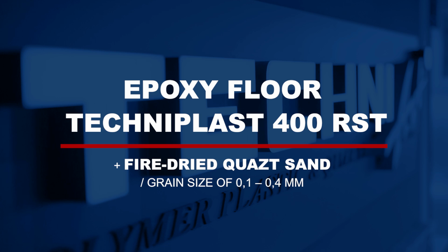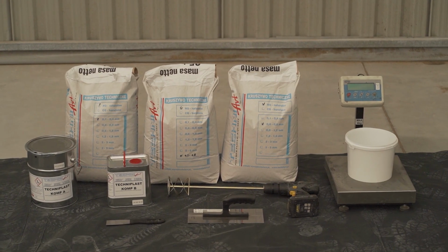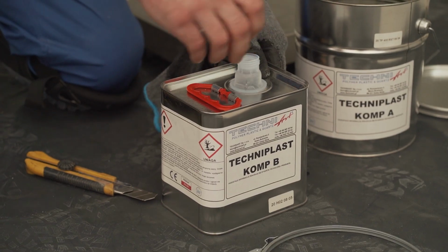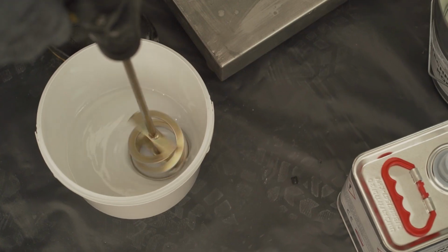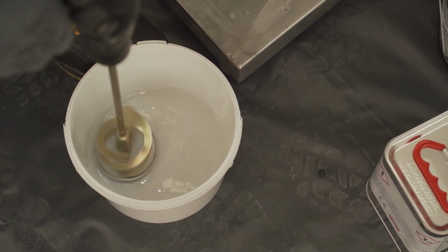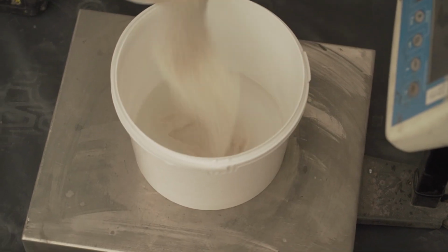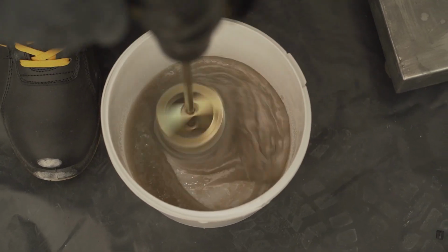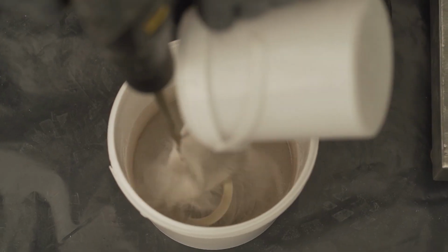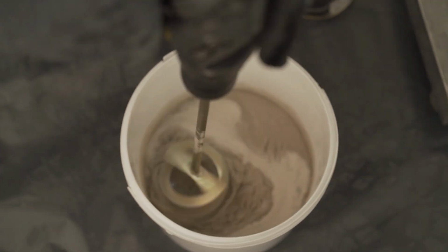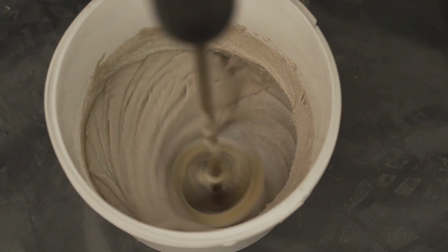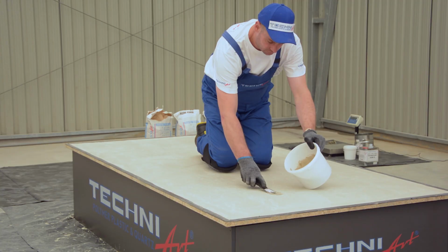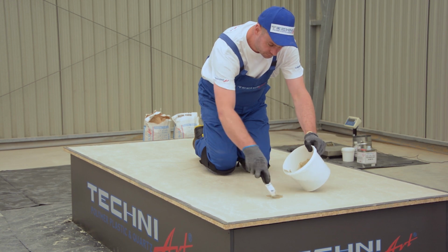The next step is to prepare the compound for filling losses and cut cracks. To prepare the putty, use the TechniArt 400 RST, and fire-dried quartz sand with a grain size from 0.1 to 0.4 mm. Start the preparation of the joint compound by mixing component A with component B. Then add quartz sand and mix thoroughly. Sand should be added to the resin until a putty consistency is obtained. The prepared mass should be carefully filled in the cut slots, and then all cavities should be smoothed out evenly.